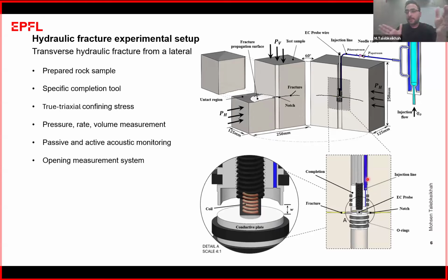Afterward, we put this sample, which contains the completion in the middle, inside a true triaxial frame where we can apply a confining stress in 3 principal directions. During the experiment, we are monitoring the pressure, rate, and volume. Also, we had an acoustic monitoring system, but in this case of sandstone, because it is really attenuative, the results were not really good, so I'm not going to present any acoustic results. I'm just going to focus on the pressure, rate, volume, and the opening that is coming from a novel technique that we are using.